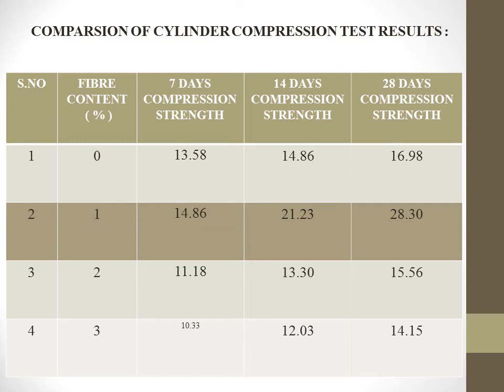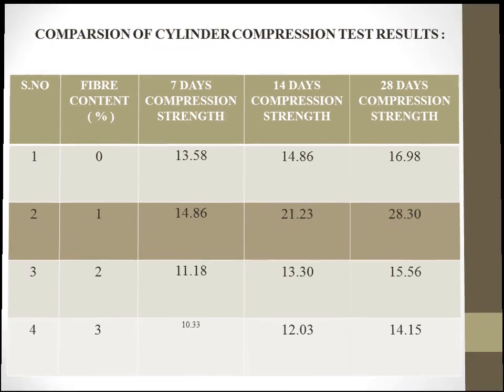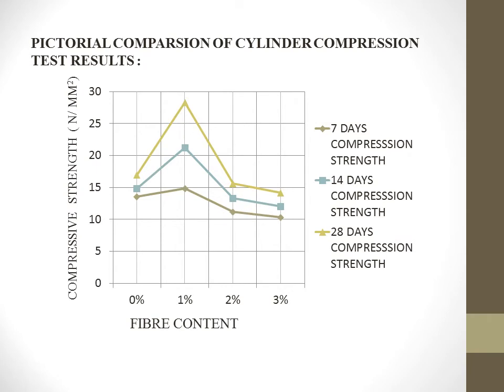As you can see, with the increase of 1% of fiber content, there is a huge increase in the compressive strength of the cylinders after curing. It has increased from 16.98 to 28.3, and then with the increase in the fiber content, there is a decrease in the compressive strength. There is a great jump from 0% to 1% fiber content, and then there is a gradual decrease with 2% and 3% of fiber content.